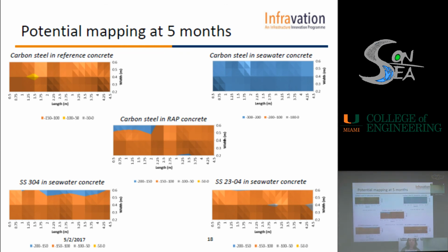We also performed potential mapping. These are the maps that we obtained. The colors are not really meaningful, but the aim of this mapping was to check the corrosion condition over all the segment that is 5 meters long. We should remember that when we use an embedded reference electrode or any other probe, we obtain information on the potential or any other parameter in the vicinity of the probe itself.